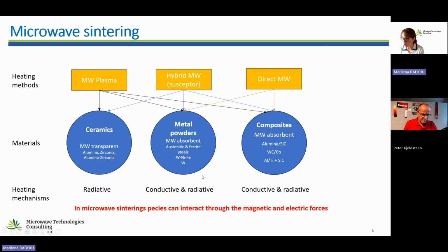So it's something that uses an outer wall that absorbs microwaves really well, and this can be applied very well to ceramics, and to metal powders, but we don't really care about that because the metal absorbs, and it can obviously apply to the composites. So in terms of heating mechanism, once again, we have radiative heating for ceramics, either by hybrid or microwave plasma, and we have conductive and radiative for metal powders, and the same for composites.